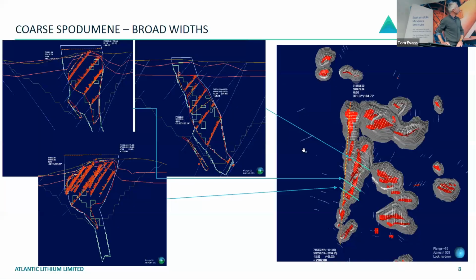So here are some cross sections of the pegmatite. On the right here in red, you can see the 0.4 mineralization shells. So these are the pegmatites at greater than 0.4% lithium oxide. And in gray are the pit shells that have been designed around that. And then some cross sections through there. So this is what we call our main Ewoyaa trend, that north-south trend. And then you've got these more east-west pegmatites, which is what we call our Abonku trend.